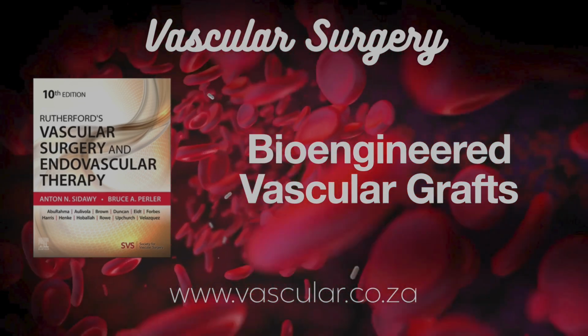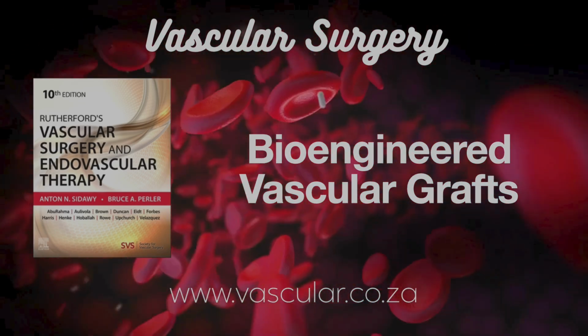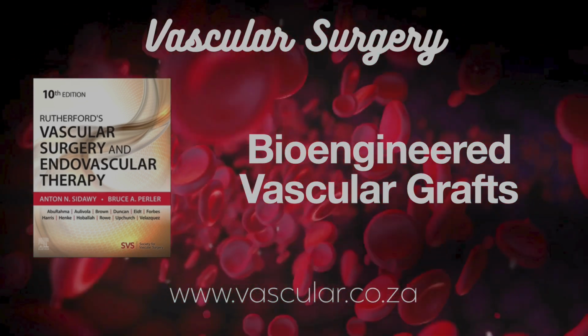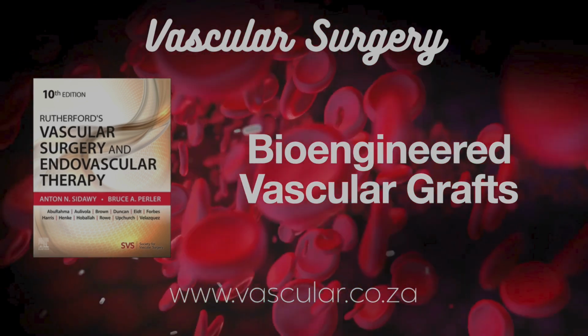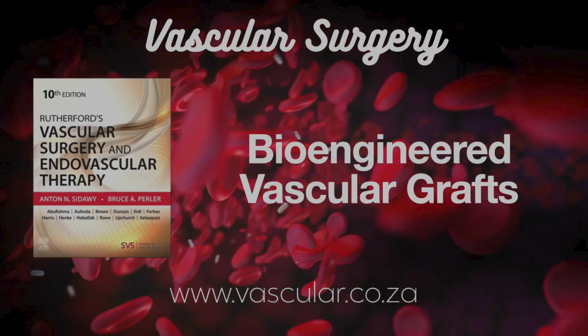Okay, last category. Tissue-engineered sheets, building layer by layer. Right. Instead of seeding cells onto a preformed scaffold, you grow the cells, smooth muscle cells, fibroblasts, into confluent sheets in culture dishes. Like a sheet of living tissue. Yeah. Then you carefully lift these sheets and wrap them, layer by layer, around a temporary tube or mandrel. You let them fuse together to form a vessel wall. Does that work? Is it strong enough?